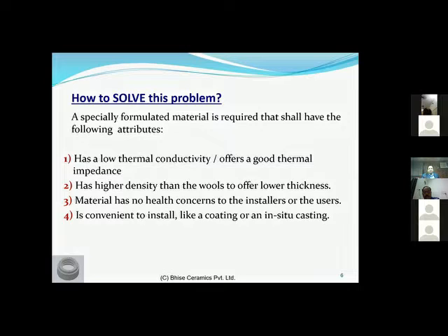So overall, if you have to categorize an ideal insulation material, it would meet these parameters. It should have low thermal conductivity. That means it should offer a very good thermal impedance. It should have higher density than the wools, so we can go for a lower thickness. Of course, it should not be as dense as the bricks; it should have a lower density than the bricks, but higher than the wools.